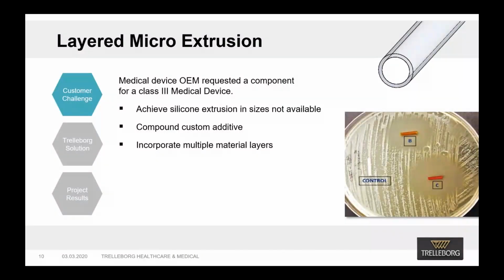In this case, the device OEM needed an extrusion small enough to challenge the capabilities of the most precise silicone extrusion processes. Typical dimensional limits prior were roughly 7 thousandths of an inch inner diameter by 15 thousandths of an inch outer diameter, or 0.18 millimeters by 0.38 millimeters. The request included compounding of a custom additive into the silicone at a precise concentration to employ the silicone's permeability properties and elute at a controlled rate.